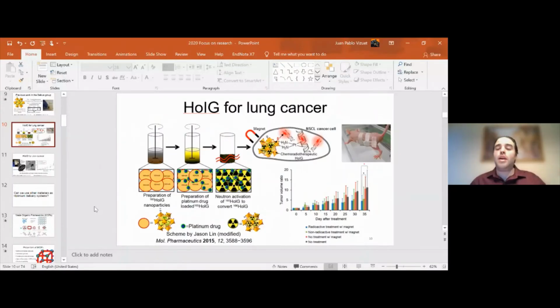Oh, no. Just going back to it, let me go a little bit to the intro. We were trying to replicate what we have done in the lab before, where you have these magnetic particles, in this case holmium iron garnet. By putting an external magnet, you can try to direct them to the tumor site. I did mention one of the few drawbacks of this material is that the magnet strength is not as high as you desire. So you need to work with a lot of big magnets, and the deeper you go into the tissue, the harder it is to get.